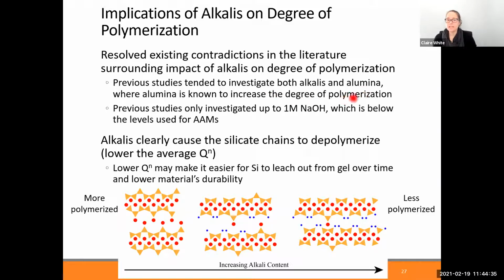And so that's important to understand. One way of offsetting this depolymerization that occurs from the sodium is to make sure you have an ample source of alumina to incorporate into the system. And then the other thing is we went to quite high sodium concentrations, beyond which the community has looked at in the past. And we saw even further depolymerization occurring, which we need to be careful about when it comes to what properties the real gels have when we use them in a concrete.